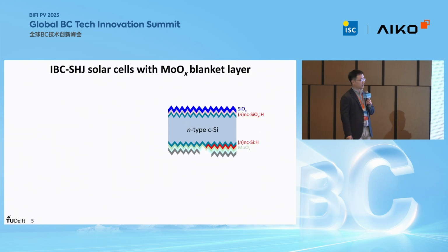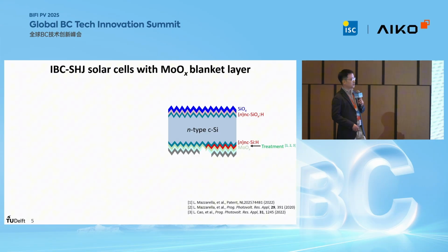In this device, we have on the front side an intrinsic amorphous silicon passivating layer, then a very transparent N-type nanocrystalline silicon oxide front surface field layer, and on top, a silicon oxide anti-reflecting coating. On the rear side, we also have an intrinsic amorphous silicon passivating layer on the full area, then a deposited nanocrystalline silicon layer that we pattern, and on top, we deposit a full area molybdenum oxide layer. Before the deposition of the molybdenum oxide layer, we also apply a plasma treatment that enables the molybdenum oxide to feature a proper high work function and also sufficient oxygen content in the material. Then we finish the device with the TCO and metallization.